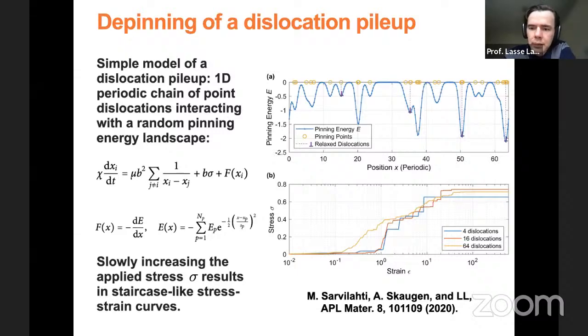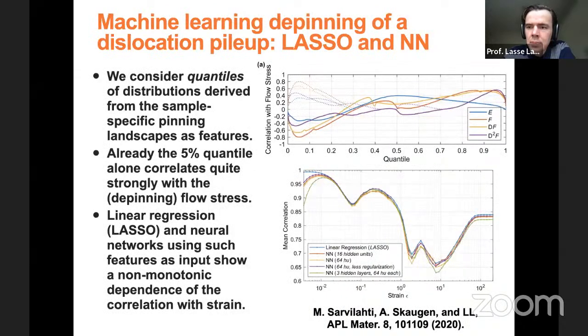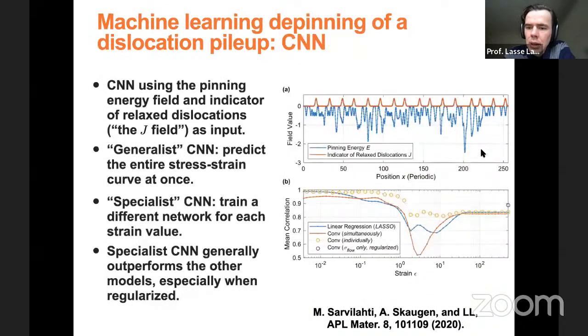Yes, indeed, that's one of the things we did. So let me try to show you. Here, for instance, these are the predictions for different models of the stress at a given strain, for different strains. Now the prediction of the flow stress is basically what happens here at the large strain. Most of these models give a correlation of 0.8 something. If you fine-tune your model very carefully, you can get up to about 0.9 correlation of the flow stress using the information from the initial configuration.